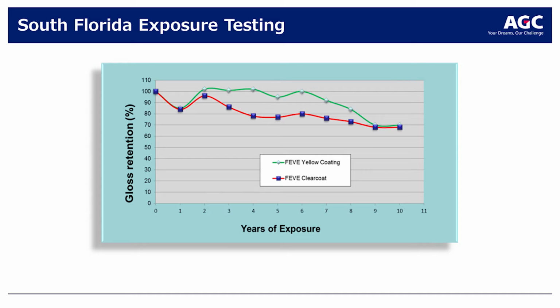And here what we've done, we've tested this in South Florida. So they have exposure cabinets and panels that they load panels onto these racks, and they put them south-facing, usually at a 45-degree angle. And then over time, they look at gloss retention. And we pick gloss retention because it's easy to measure. There are instruments you can take out in the field and measure with it.